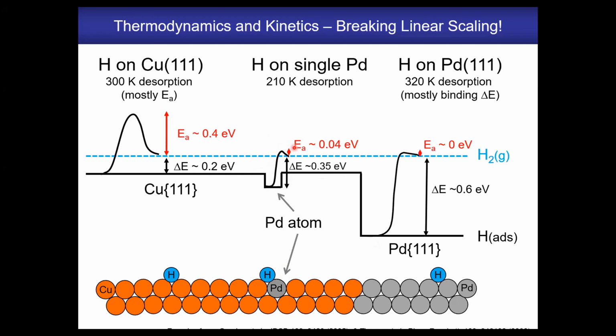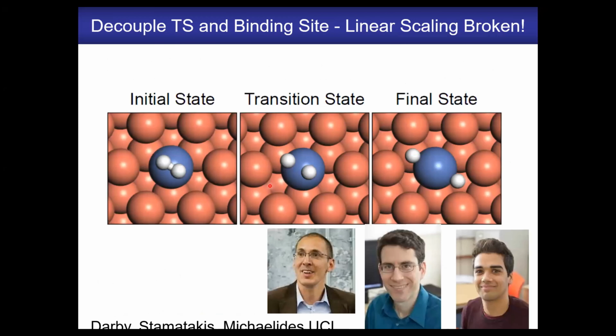We have a low activation barrier and we have weak binding of the hydrogen. And the reason for that is that the location of the transition state and the final state for the dissociation are decoupled. So in a simple sense, the transition state is benefiting from the palladium atom's electron density in order to lower that energy, whereas the final state has the hydrogen atoms bonded to 2 copper atoms and 1 palladium. So it has a fairly weak binding strength, which decouples the two and allows you to have low activation and